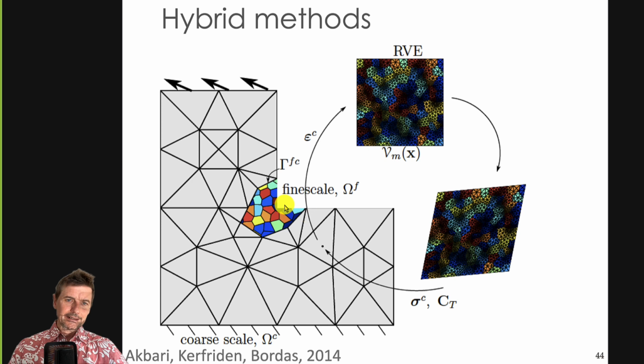Well, because you started with one element that has a whole history of loading. The integration points were loaded up to that point, and they went through plasticity, through a lot of time-dependent variables that now, if you have to replace those by grains, you essentially need to reload the whole granular structure in order to allow that structure to live the same life as the integration points, the material point that was there before. So you need to reapply the history of that material point to these little grains so that they have the memory of this material point that was there before.